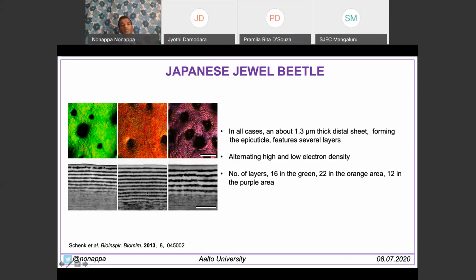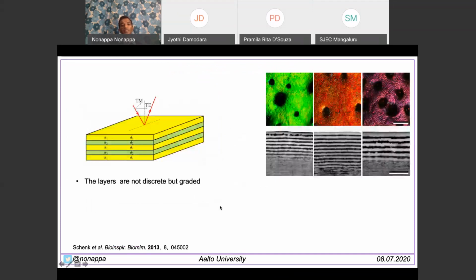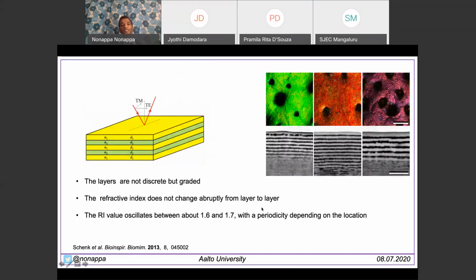There is a nice periodicity, but this periodicity is not very regular. And because it's not regular, they are able to modulate the light and change the color rapidly if they want. So this shows that simply by changing the same object here, which I think is made up of chitin and melanin, they have different refractive index, so they have different electron density. And just by the thickness and the number of layers, you can change the color using exactly the same material. So this saves a lot of energy, resources, and time for materials.